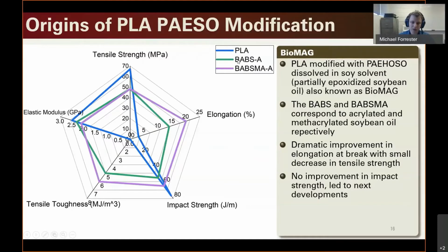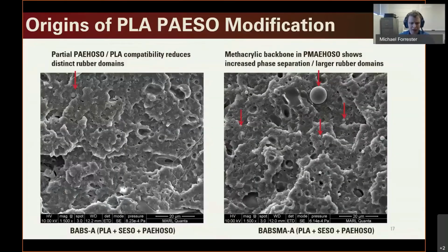So sample codes here, this BABS is PLA with biomag, and this BABSMA is PLA with a methacrylated PAESO system. And what you find is that the incorporation of those two materials can lead you to between 12 and 20% elongation at break, whereas virgin PLA is around 3 to 4%. So you dramatically improve the tensile toughness of the material. But we didn't see an increase in impact strength. In fact, we saw a slight decrease.